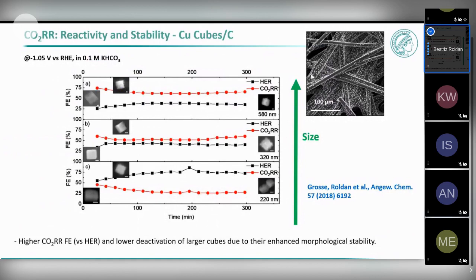You see here the same cubes on a carbon paper support, and these are very large, in this case 600 nanometers or 200 nanometers, but there is a very clear size effect. In red is when we are producing CO2 electroreduction products, and in black is when we are making hydrogen. And so for the large nanoparticles, nanocubes, we make more CO2 electroreduction products than hydrogen. But if you go to smaller particle sizes, the cubes start to become more unstable, they break up, they form a lot of small particles, and they favor the production of hydrogen. So you see here the increase of the hydrogen production at the expense of the products that we want to make. So this structural instability is reflected in changes in the selectivity.